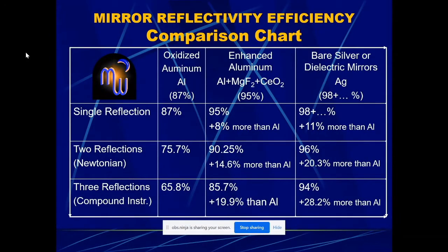So here's a chart just giving you an idea as to the efficiencies of the different types of coatings and how many reflections you're dealing with. As you can see, let's say we had 3 different reflections or so, you'd be down to 66% efficiency with bare aluminum. But with enhanced aluminum, we're up to 86%, which is a 20% improvement. And then if you had silver or a dielectric mirror, for example, you'd be up to 94%. So it gets pretty good. That's why it's a necessity that mirrors get enhanced aluminum.